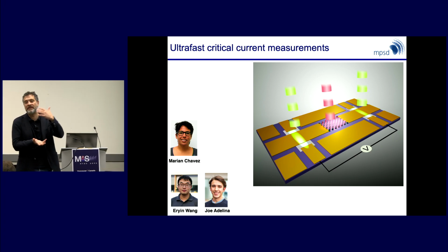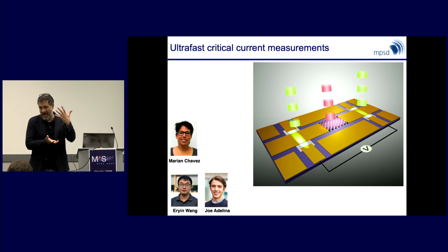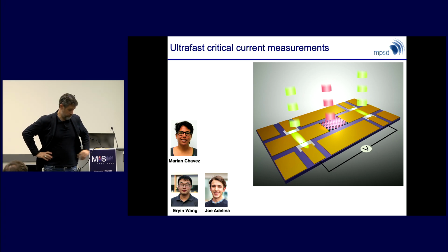And you have a superheated superconductor, imagine, and now you have a rate-limiting timescale that depends on some rigidity. But I think that the relaxation rate will depend on things like the phase stiffness of this light-induced state or other phenomena. So in a Kramers picture, it is more the curvature of the parabola of your metastable state rather than the height of the barrier and the thermal fluctuation.